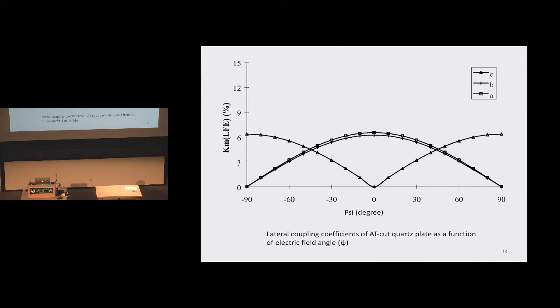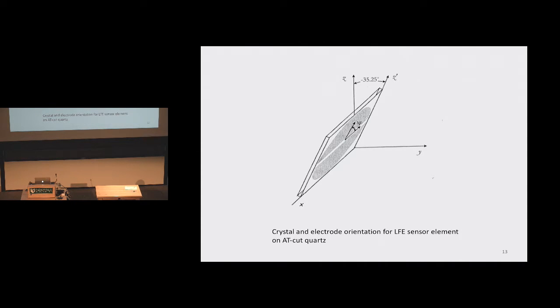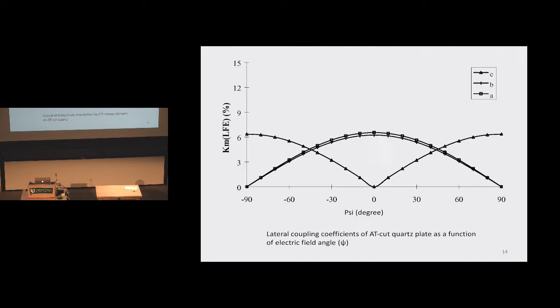And here are the actual calculations on that. This is that psi angle that you saw in that previous slide, namely this angle right here. And what that indicates is that if you're 90 degrees away, or minus 90 degrees away, the coupling to that transverse shear mode, which is given as mode C, is finite, and the coupling to the other two allowed bulk acoustic wave modes, the longitudinal and the other shear, is 0. Over here, a similar sort of situation. So it basically says, yeah, you can put those electrodes on there, make sure that they're oriented so that the electric field is either plus or minus 90 degrees.